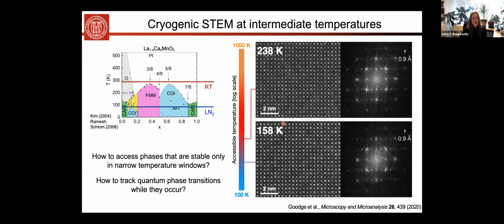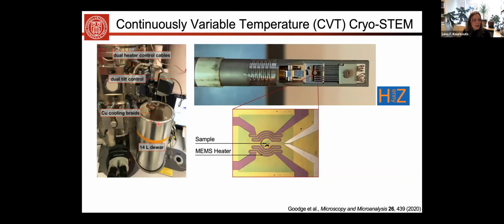And so what I now want to show you here is that we have also been able to obtain stable sub-angstrom resolution imaging at all temperatures between about 100 Kelvin and then all the way to 1000 Kelvin if you choose, all done in one cryo setup. And that now allows us to really probe transitions and how the atomic lattice responds in real space. Okay, so how do we do this? So let me walk you through it. On the left is an electron microscope.